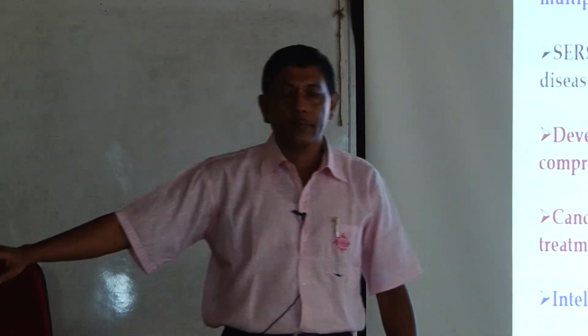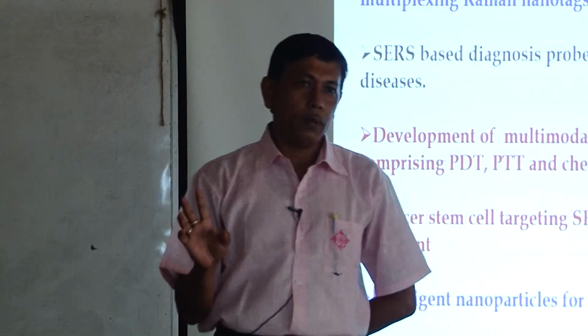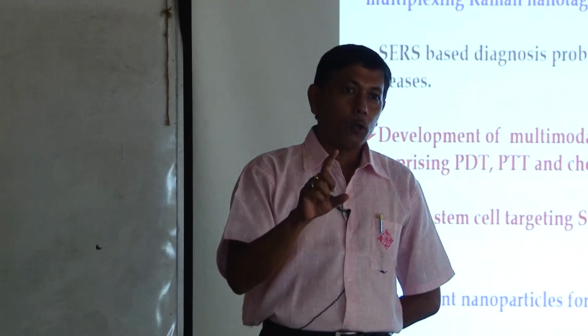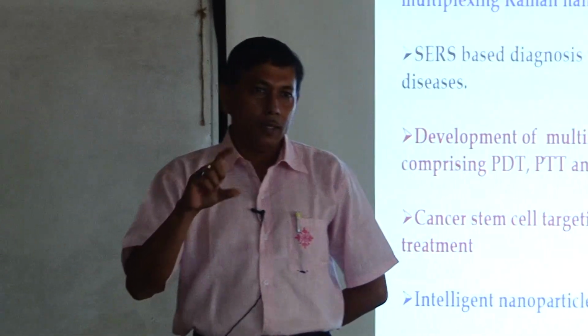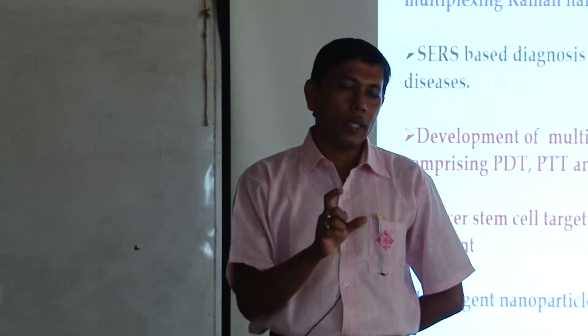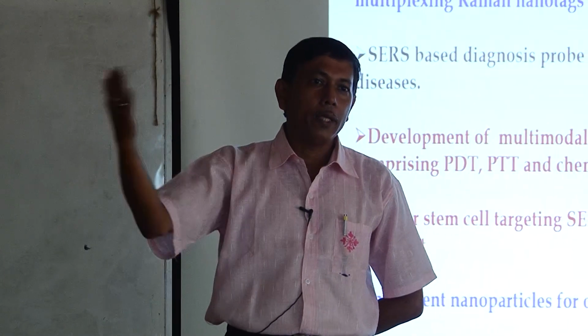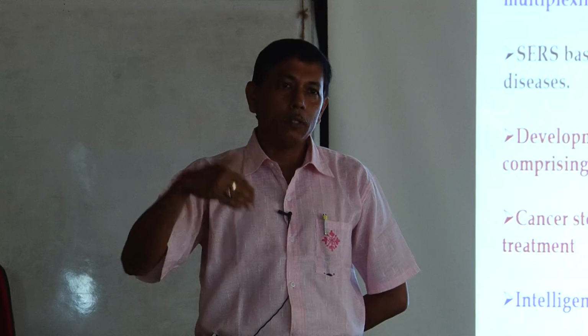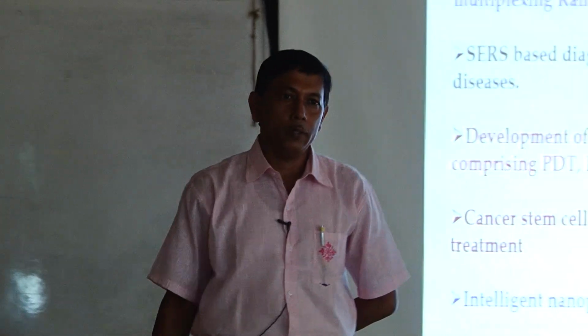Then in one of the slides, MRI is there. Yeah, that is the Fe3O4 incorporated slide. Is there any use of gold nanoparticle in MRI? No, gold nanoparticle has nothing related to MRI. Gold nanoparticle is used for surface enhanced Raman, but iron oxide, which is used either as a coating agent on it, can be used for MRI. So, you can do both MRI and Raman simultaneously.